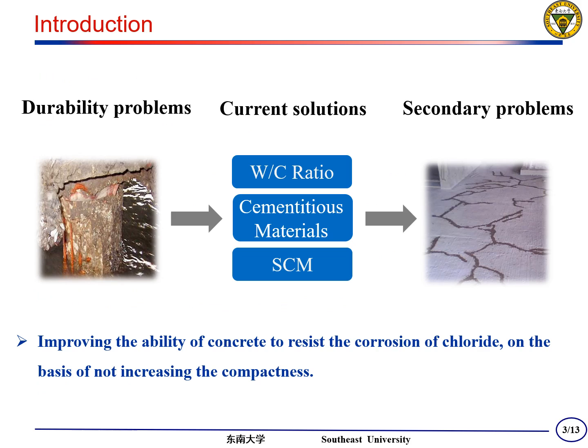The ingress of deleterious ions, such as chloride, in reinforced concrete structures is essential to determine the service life. At present, measures to mitigate the ingress of external ions in concrete mainly include reducing water-cement ratio, increasing the quantity of binders, and adding supplementary cementitious materials, most of which aim to densify the binder matrix in concrete.